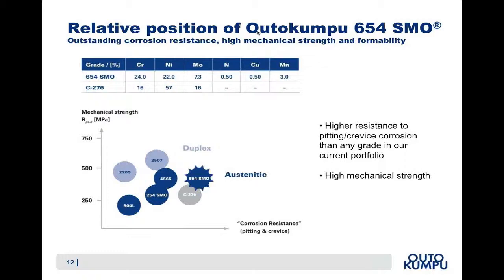And if we look at the values in the table above the chart, where we compare 654 SMO with C276, the most remarkable value to note is, of course, for nickel. Despite 654 SMO having only 22% nickel compared with C276's 57%, 654 SMO provides at least equal and often superior corrosion resistance due to the higher chromium level, as well as the alloying of molybdenum and nitrogen.